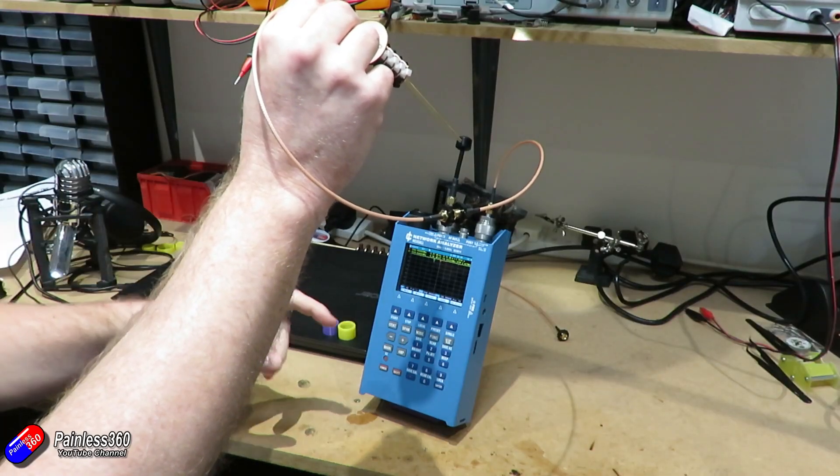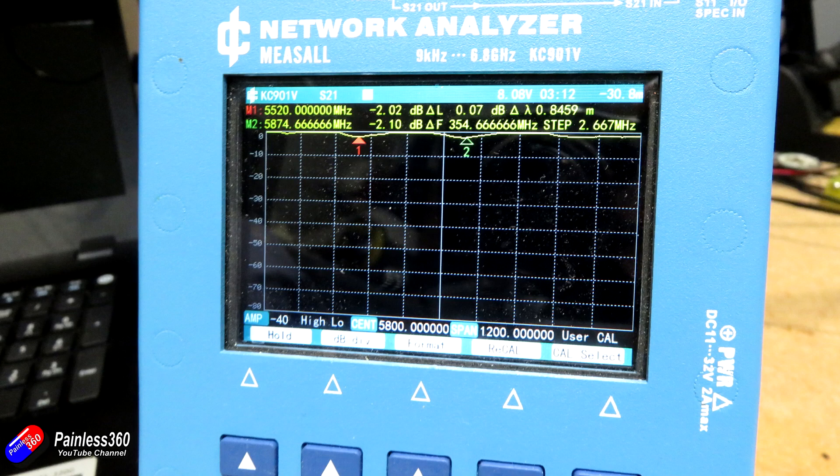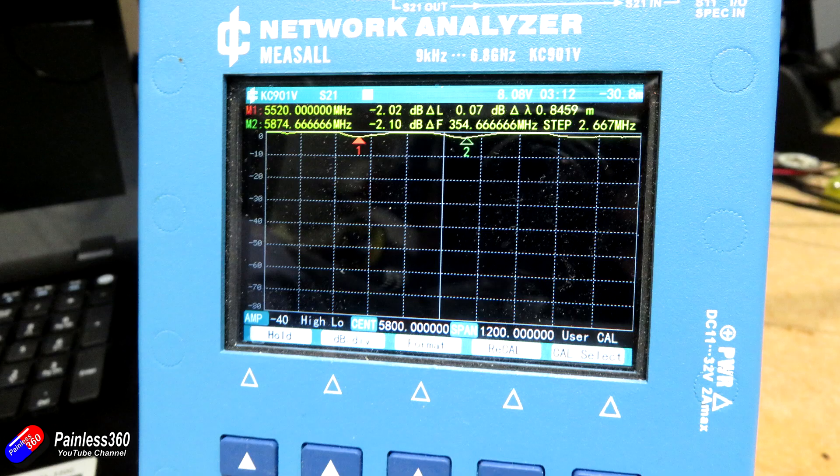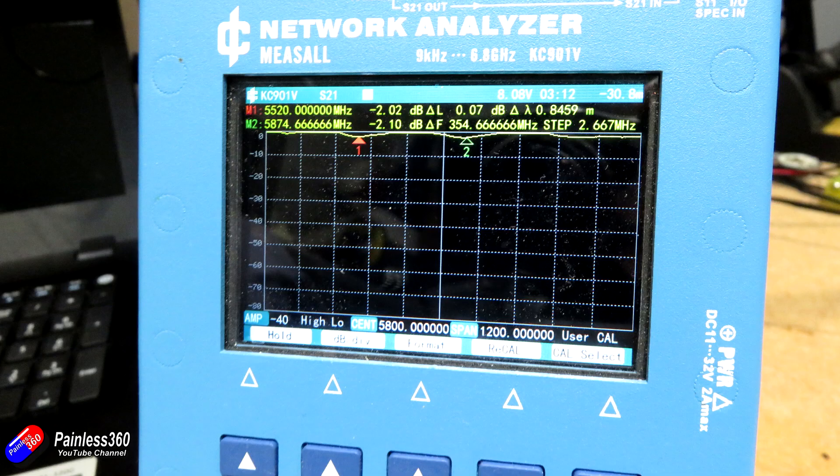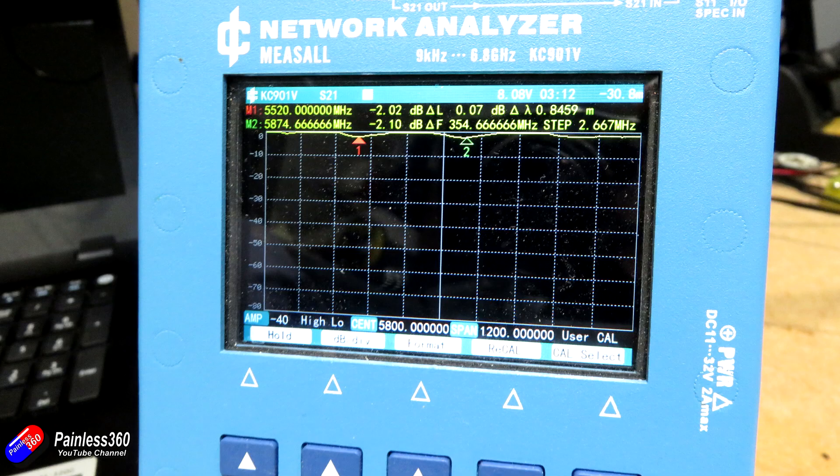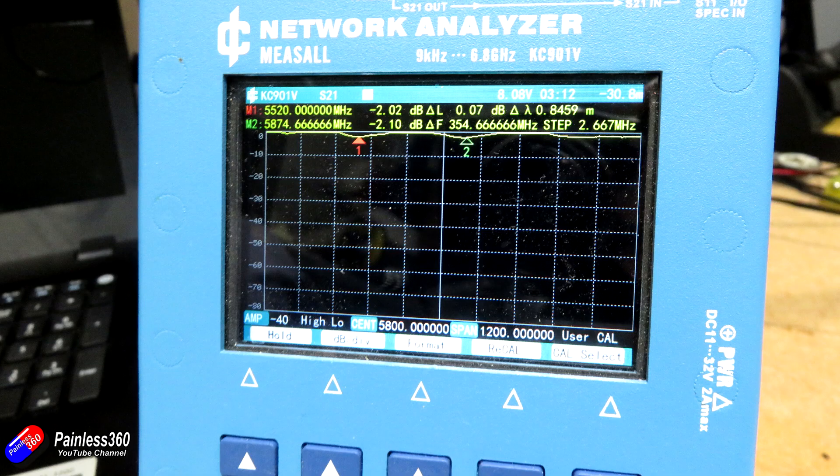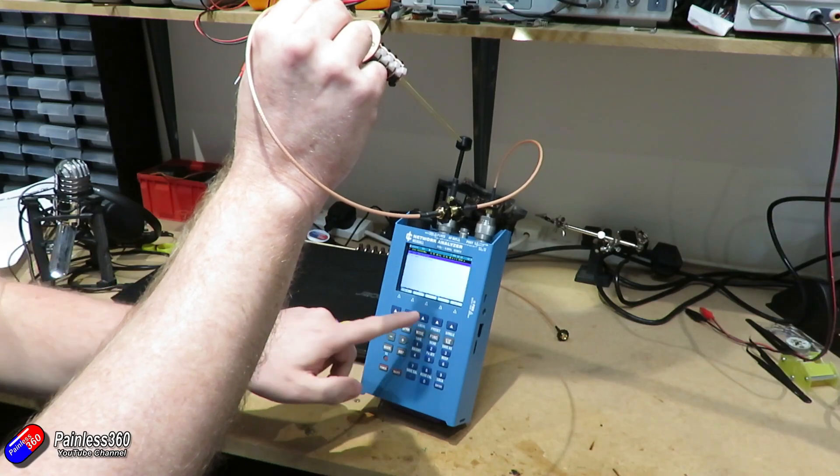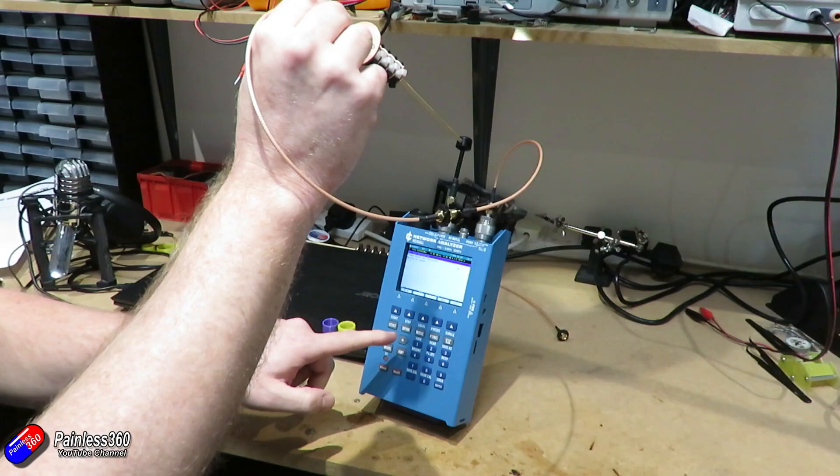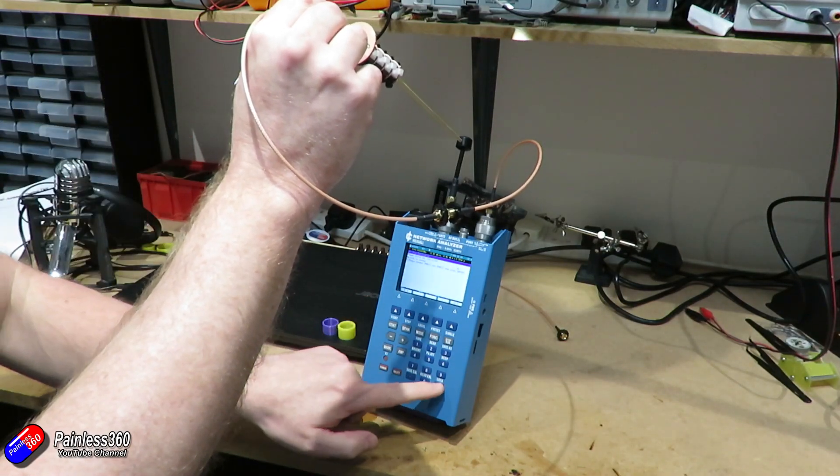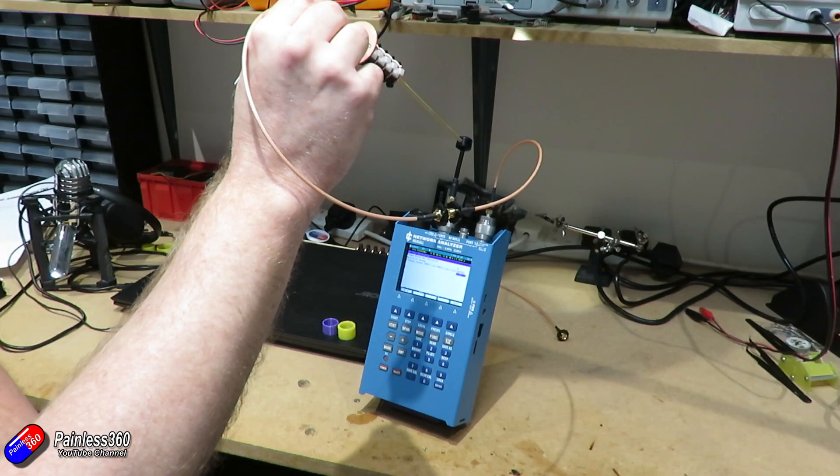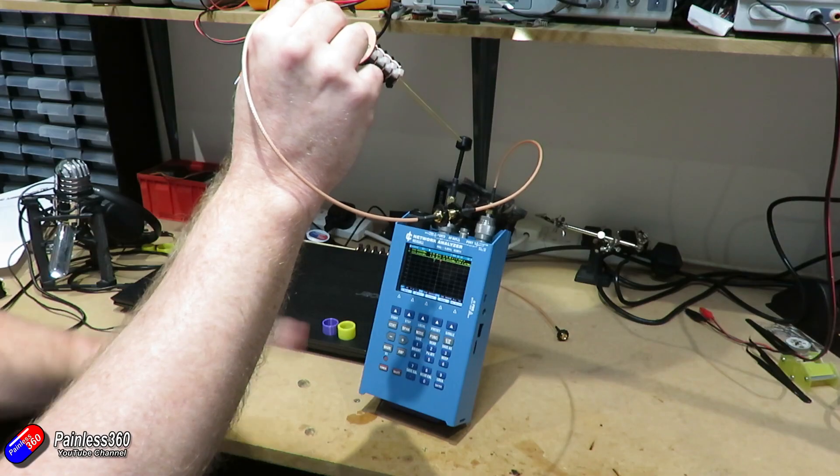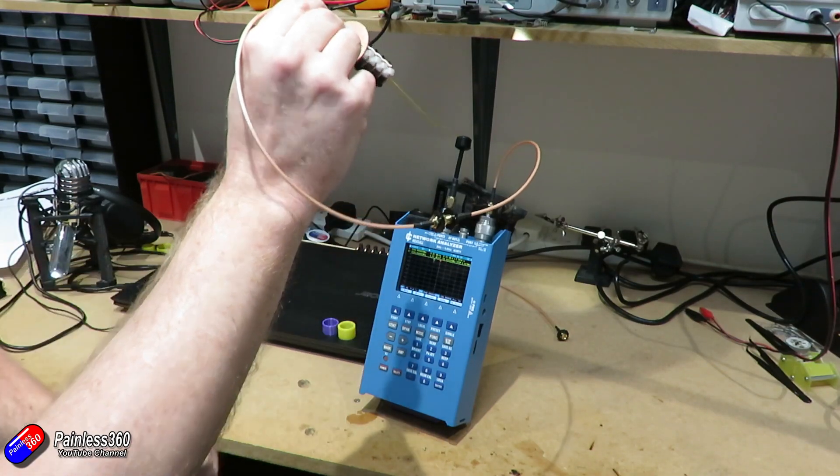Here are the results on screen. Greg, what did you find about the radiated power and the effect of putting this stuff around the antennas? Basically, measurements were made with and without the shroud to figure out the reduction in signal. What we found is that with PLA, TPU, and even the Ionway with its molded cover, we were experiencing a dB drop somewhere between 1.8 to 2 dB across all those antennas. That was really interesting because irrespective of whether it's PLA, TPU, or that injection molded cover, it seemed pretty constant. We've only tested three things, so there might be better materials, but it was interesting they were all very close.